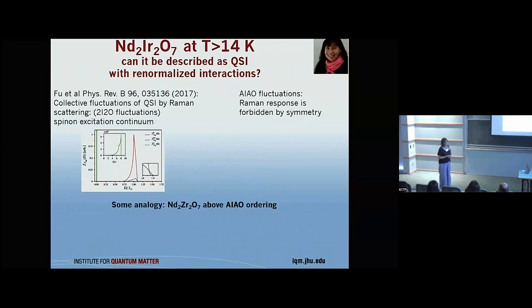And what could be the special behavior? So the system is ordering all-in, all-out at lower temperatures, but above there could be fluctuations of the state. Now, we observe a very strong collective mode, but all-in, all-out fluctuations wouldn't produce such a mode. But two-in, two-out, so quantum spin-ice fluctuations would produce a very strong Raman response.